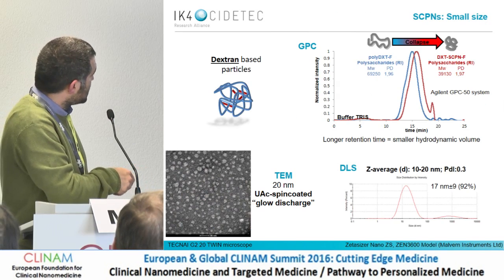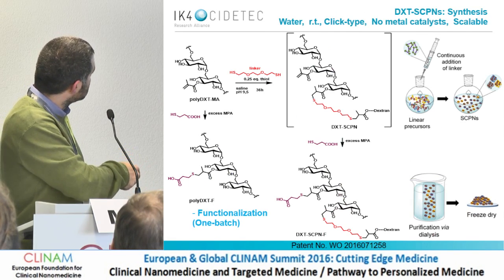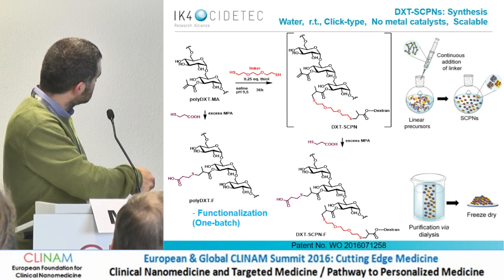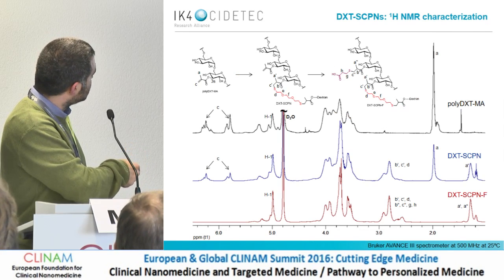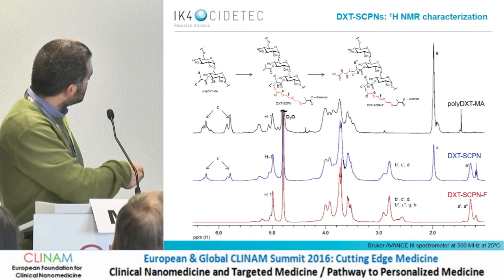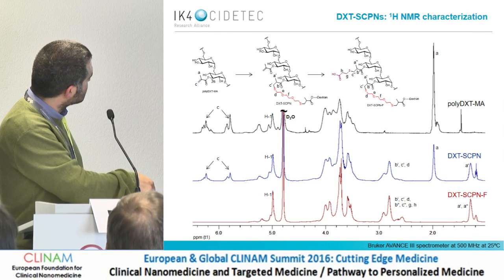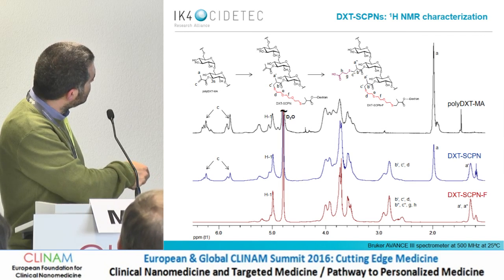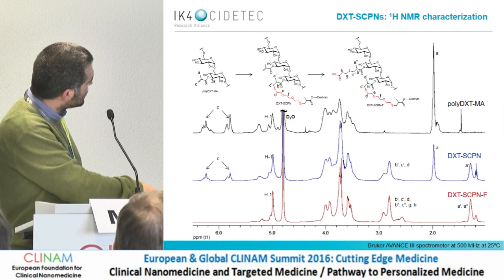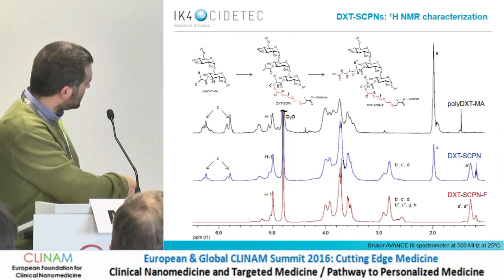A few words about NMR to follow the reaction: it is very easy to track the disappearance of signals typical of the double bond. While functionalizing with the linker, these signals decrease. A new methyl signal starts to appear. When functionalization with mercaptopropionic acid is complete, there is full disappearance of the methyl group signal and of the olefin signals.